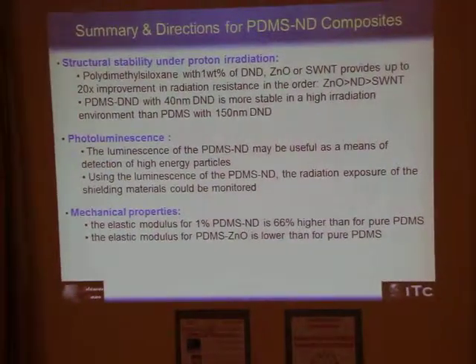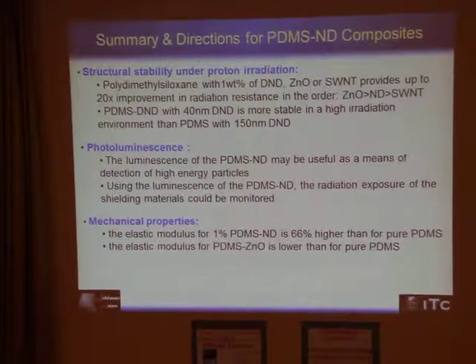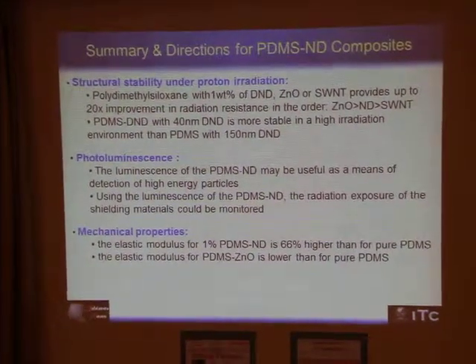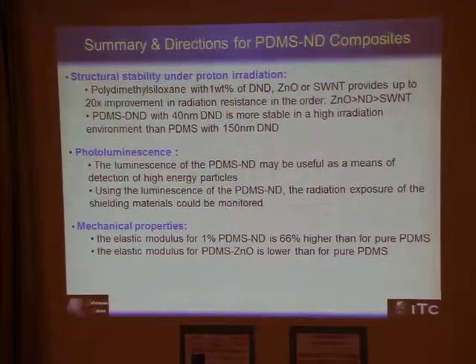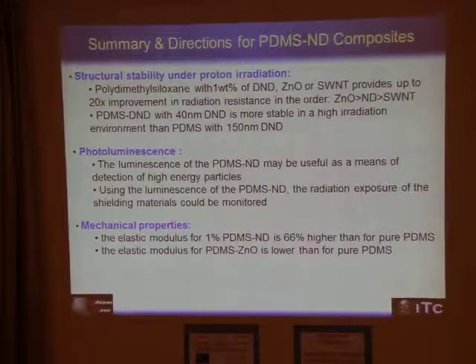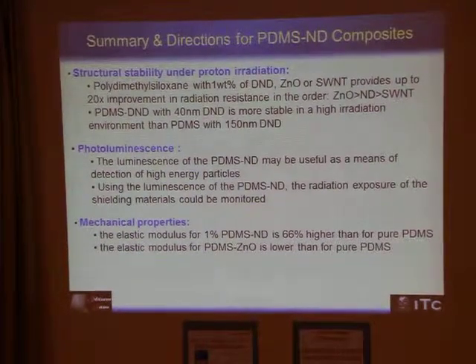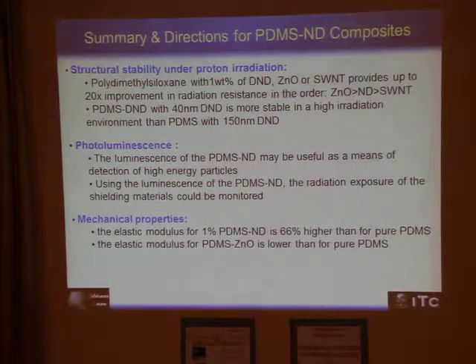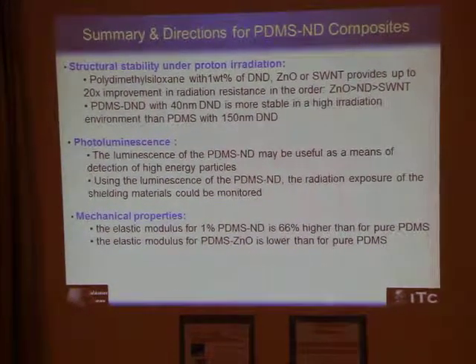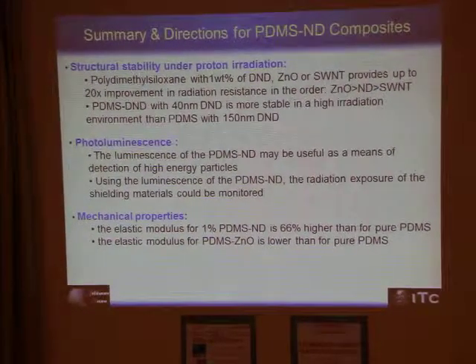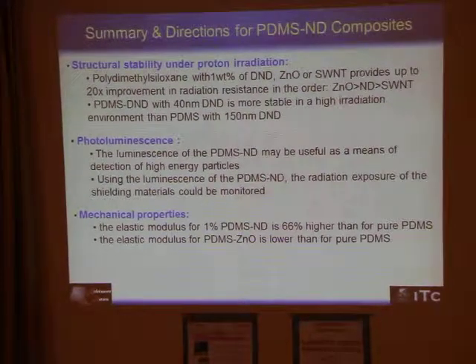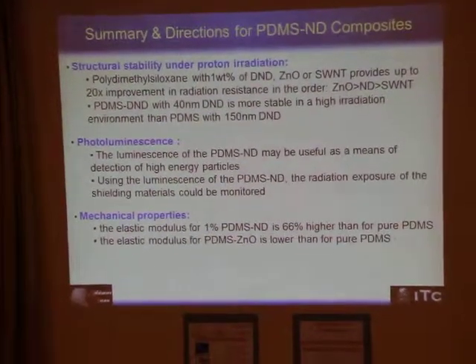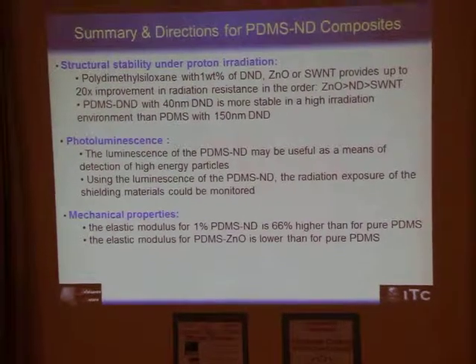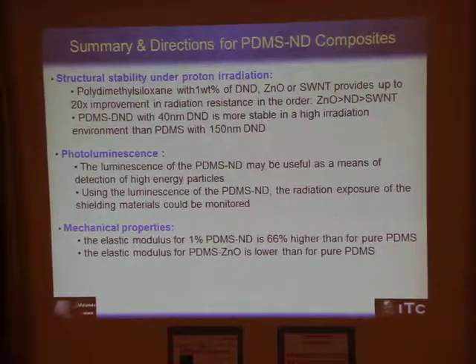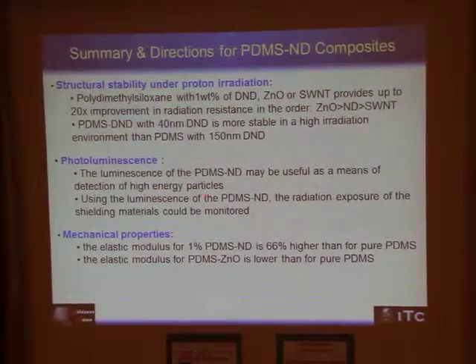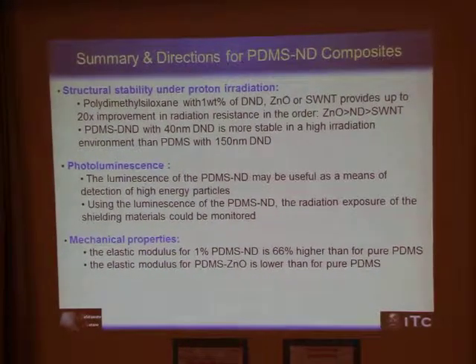So what I would like to conclude is that addition of zinc oxide, nanodiamond, and single-wall nanotubes provides enhancement in radiation resistance up to 20 times, and it can be higher since it did not reach the full structural degradation of the composites. Doses can be higher, and we still can see improvement. Smaller nanodiamonds are recommended for these applications.